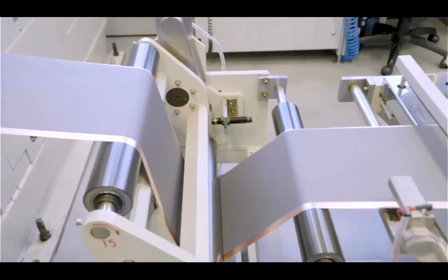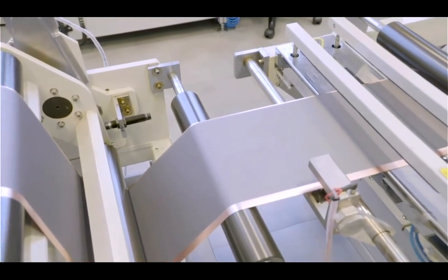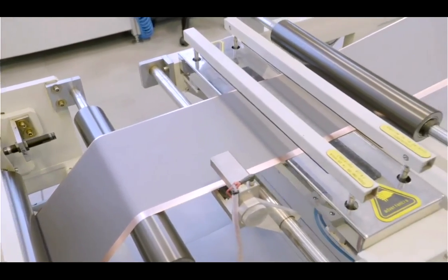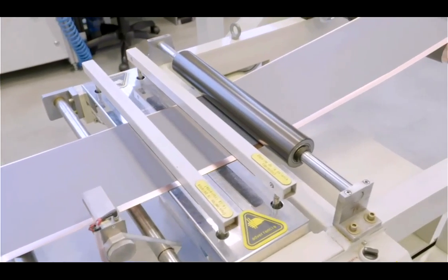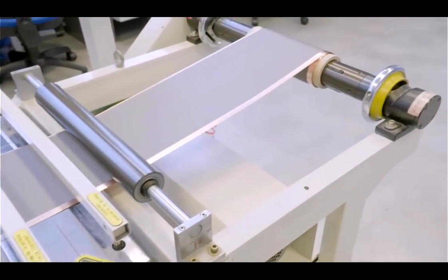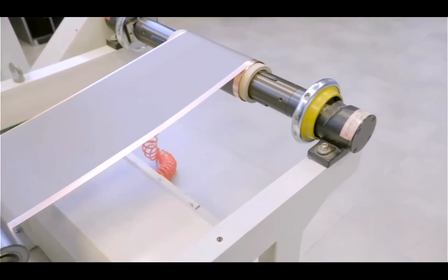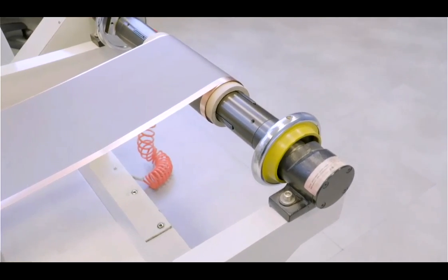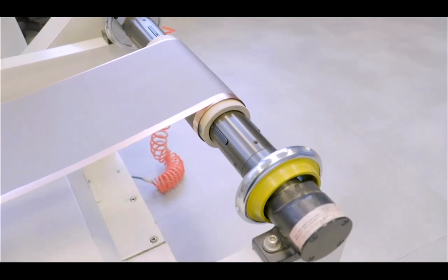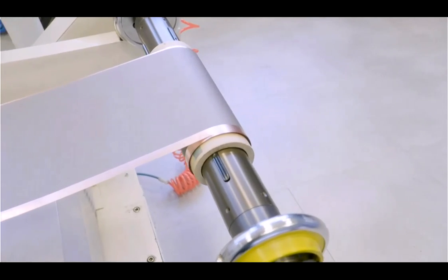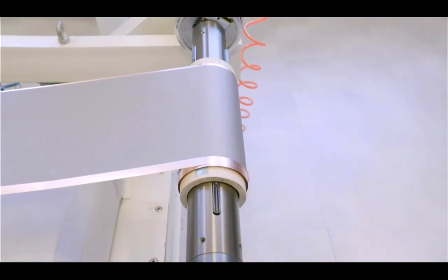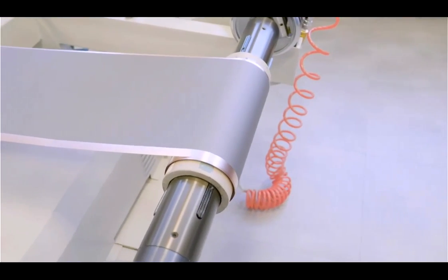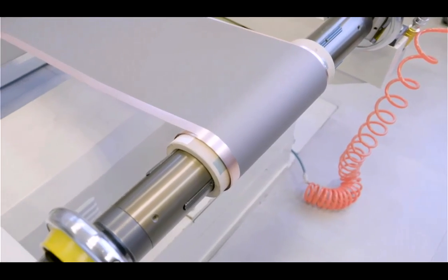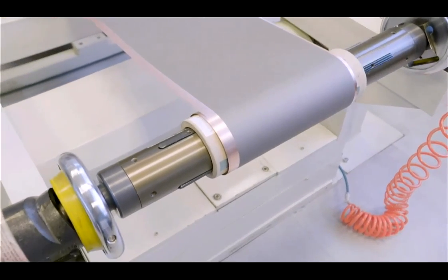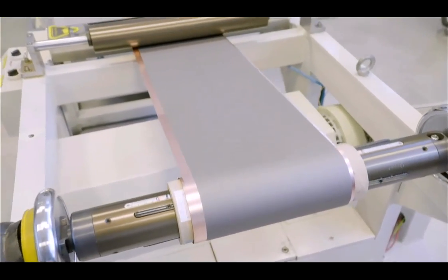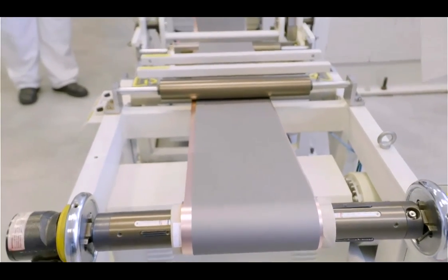And just to finalize some process parameters, to get an idea, we can increase the pressure up to 20 megapascals. The calendering speed is between 0.5 and 5 meters per minute. And one very important thing is the cleanness of the rollers. It is crucial to keep them clean, because if there is any dust or any particle and we don't remove it, it will mark all the electrode. So very important at this point.